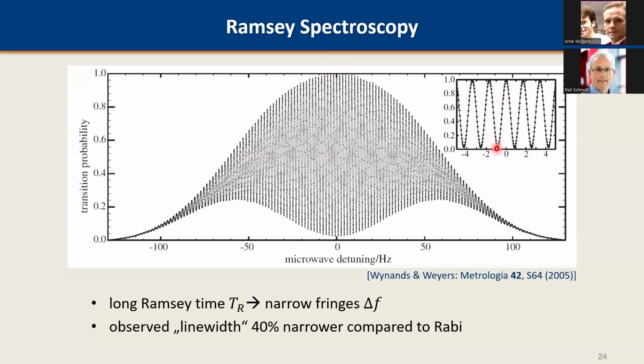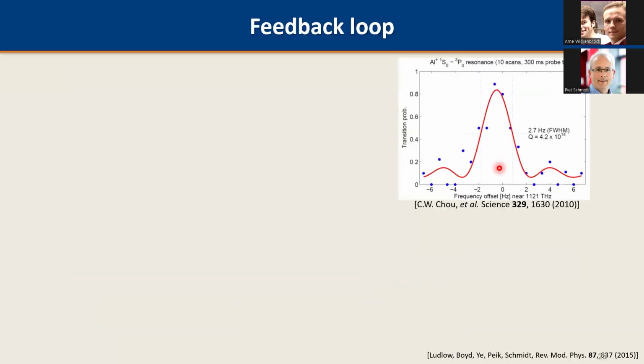And again, the longer the Ramsey time TR is, the longer the wait time here, the more phase difference you accumulate and the narrower the fringes here become. And one special feature of Ramsey interrogation is that the observed line width is 40% narrower than the comparable Rabi line width for the same duration of the experimental sequence. And that's, of course, an advantage because it gives you a higher signal-to-noise ratio. Okay, now, yes?